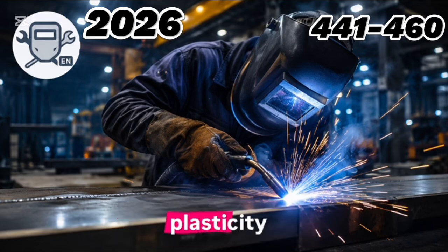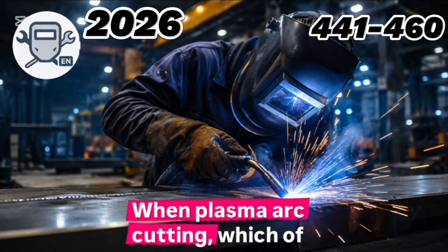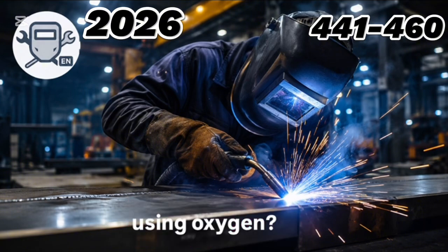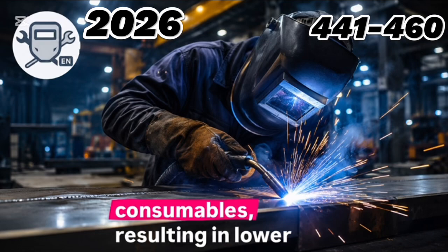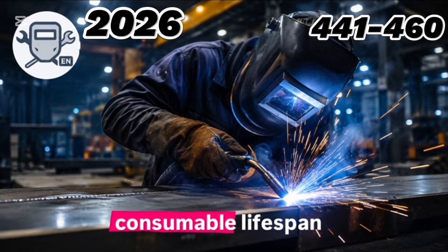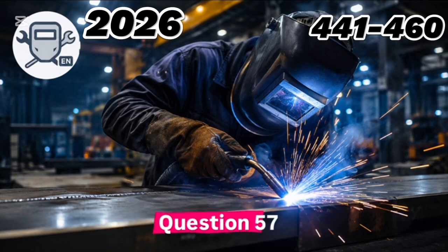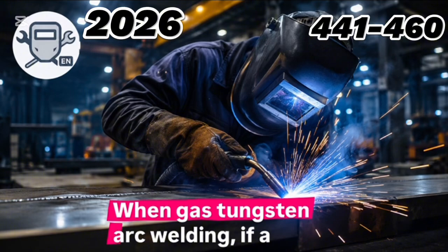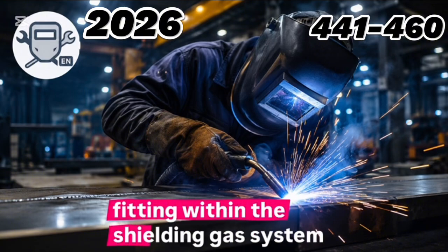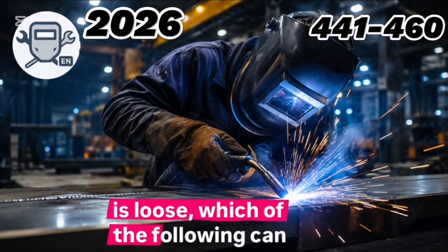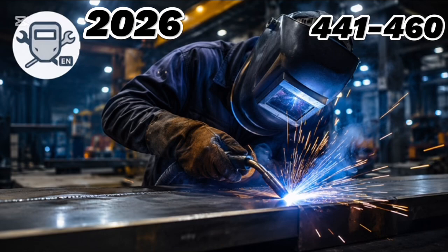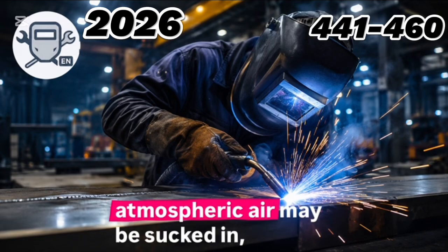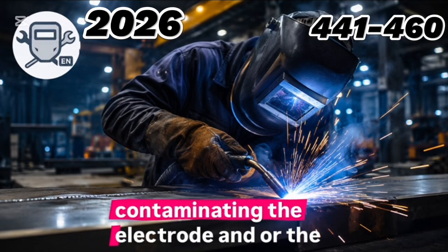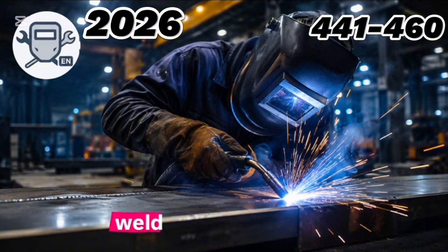Answer: plasticity. Question 56. When plasma arc cutting, which of the following is a disadvantage of using oxygen? Answer: oxygen is hard on equipment consumables, resulting in lower consumable lifespan. Question 57. When gas tungsten arc welding, if a fitting within the shielding gas system is loose, which of the following can occur? Answer: atmospheric air may be sucked in, contaminating the electrode and/or the weld.